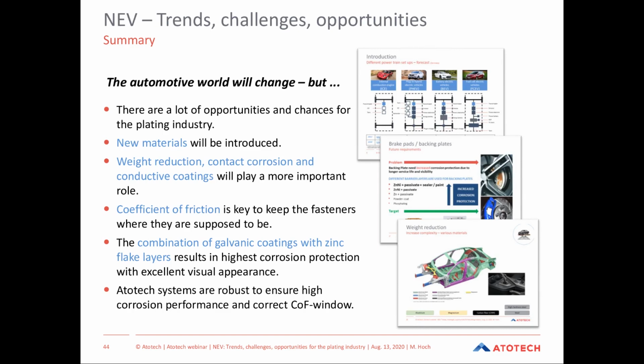Apart from that, corrosion and friction are becoming more and more important and are key to keeping the fasteners where they are supposed to be. One high-end solution for future coatings is the combination of galvanic plating with zinc flake layers, which results in highest corrosion protection with excellent visual appearance. Atotech is working very hard to make those systems robust enough to ensure high corrosion performance and the correct coefficient of friction window.